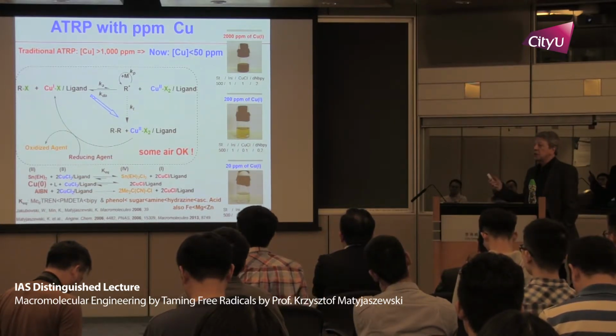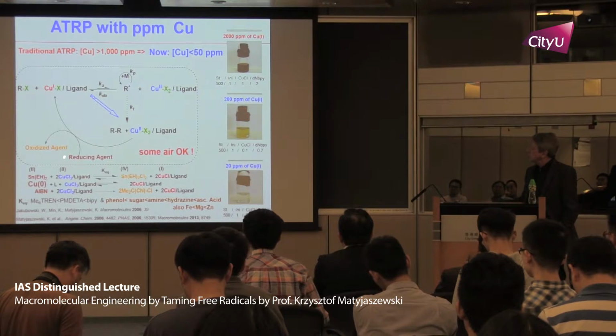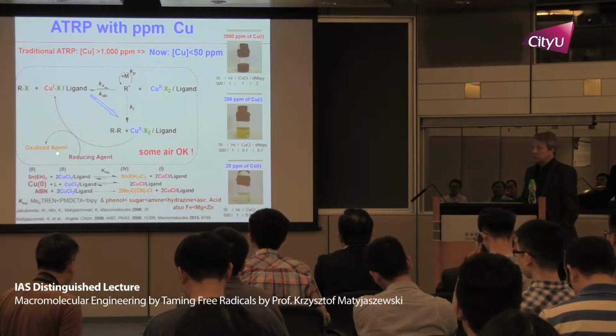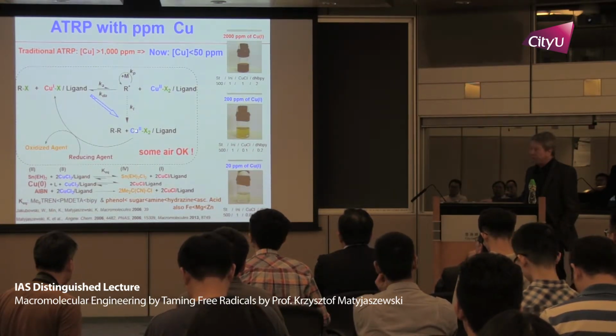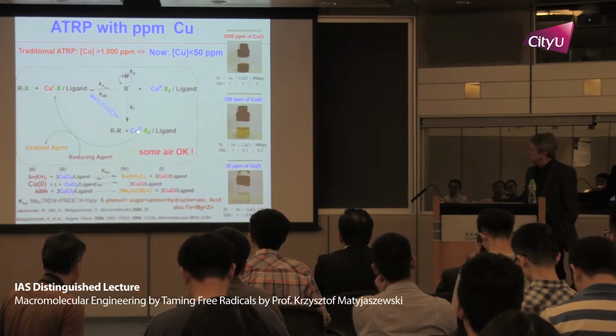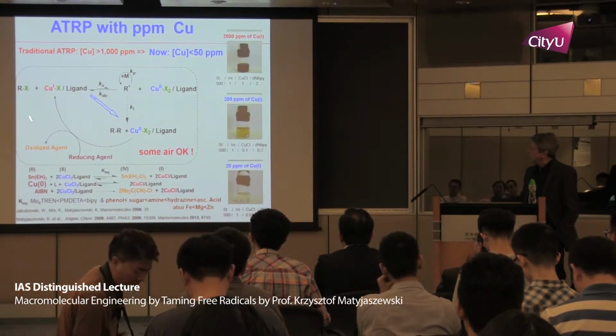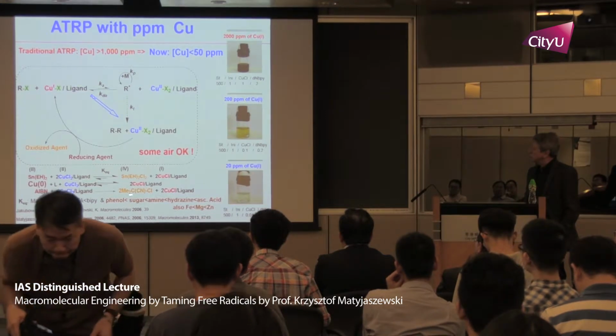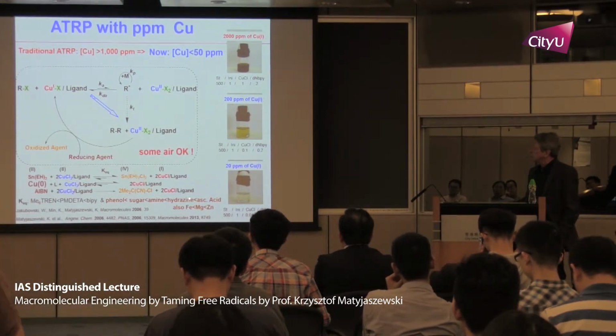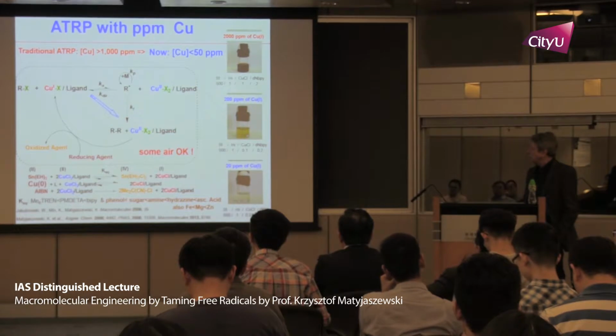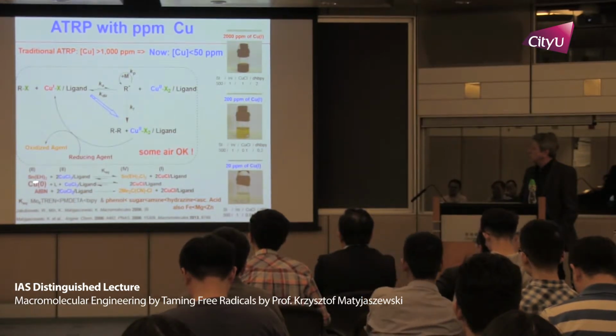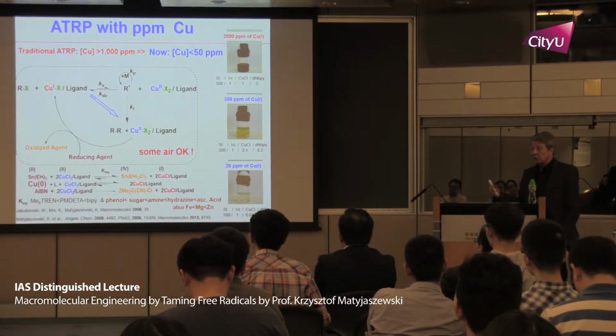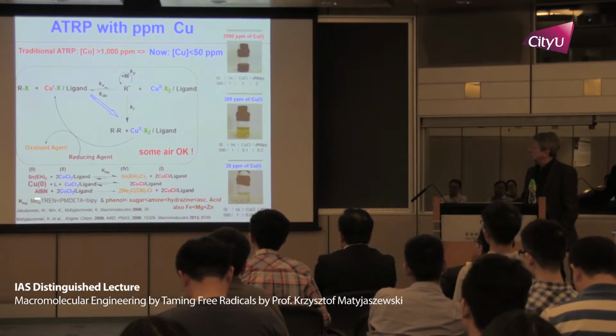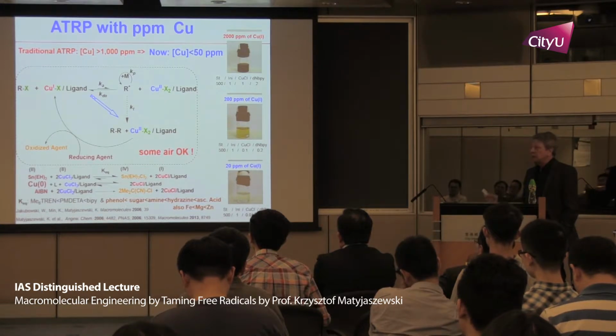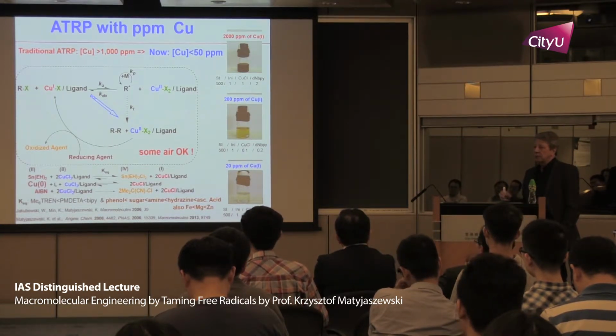So how can you regenerate this activator? You can do that in the presence of a mild reducing agent. In that case, you have an electron transfer process. You reduce copper 2 to copper 1 in the presence of, for example, sugars, phenols, ascorbic acid, vitamin C, a piece of metal. You can use tin 2 octoate, which is an FDA approved reagent. You can use a radical initiator, AIBN, in small amounts. You can use copper 0. This works very, very nicely.